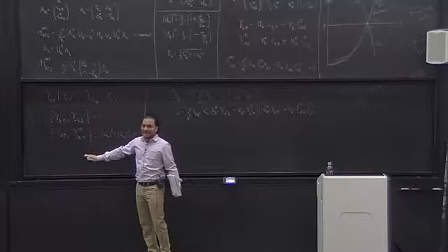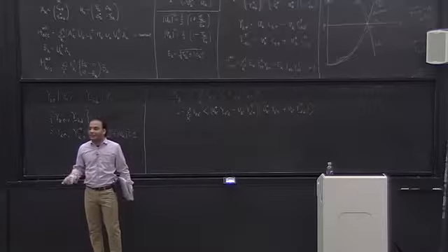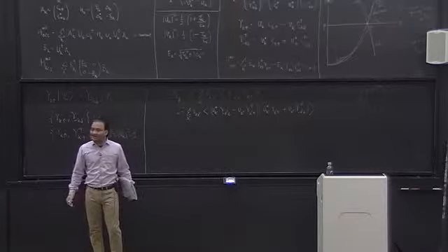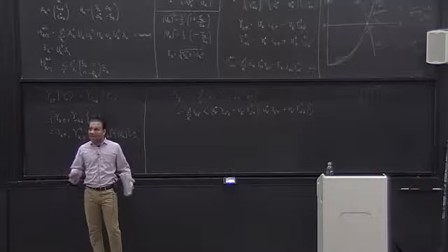So from this we already know that these gamma operators are really fermionic operators. So these new excitations are also fermionic excitations. So we have a ground state that consists of Cooper pairs, which are bosons and have 0 spin, but the excitations are fermionic.